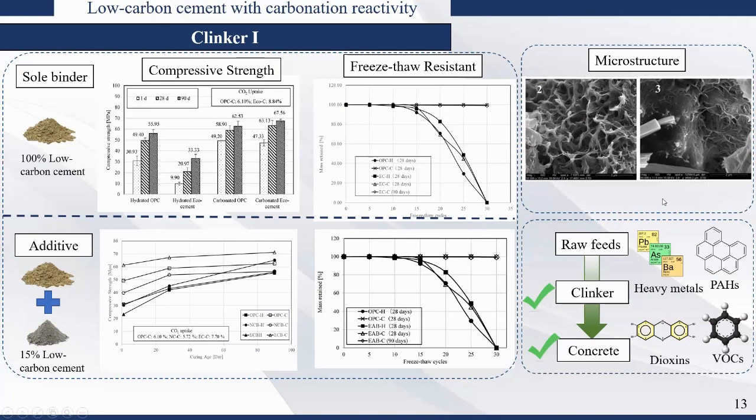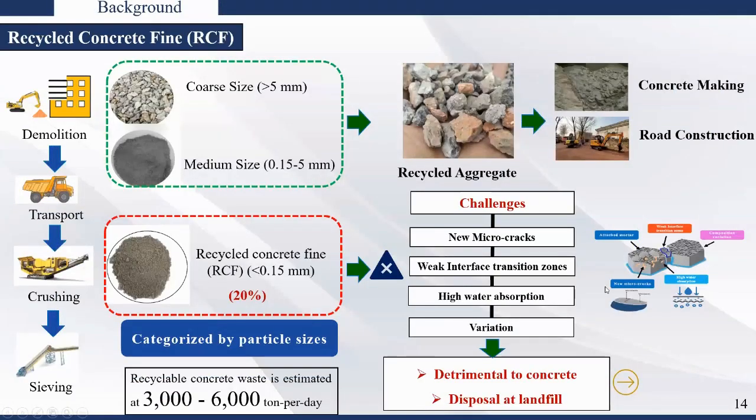Since we use solid waste, we ran a very comprehensive environmental analysis, including heavy metals, leaching, pH, dioxins and furans, and VOCs for clinker and concrete made by clinker. It all passed the criteria.